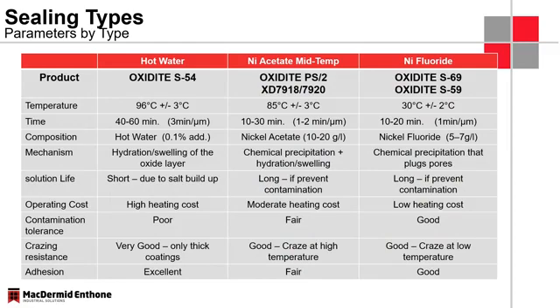The sealing, the final step of the anodizing process, really, and probably one of the most important processes to get all the good properties we expect from our anodized layers, whether this is corrosion resistance, UV resistance, abrasion resistance, and so on and so forth. And when we look at the sealing types, there are really three types we use. The old traditional hot water seal, the medium temperature or nickel acetate seal, as some people refer to, and then we have the nickel fluoride seal, or a lot of people refer to this as a cold seal.